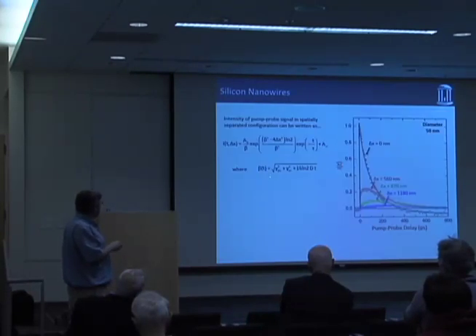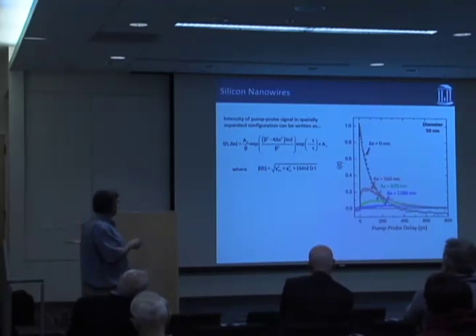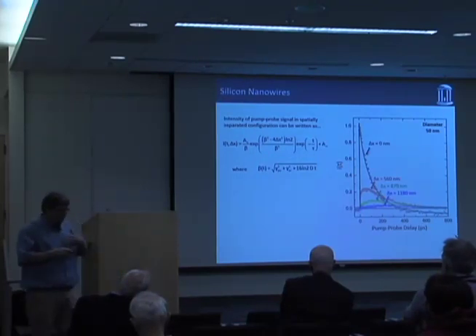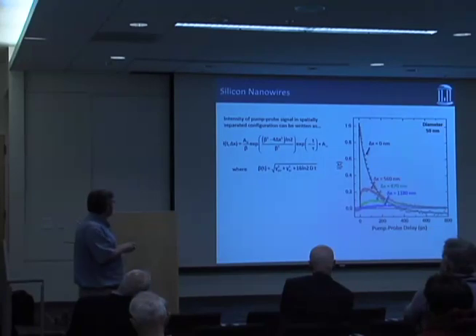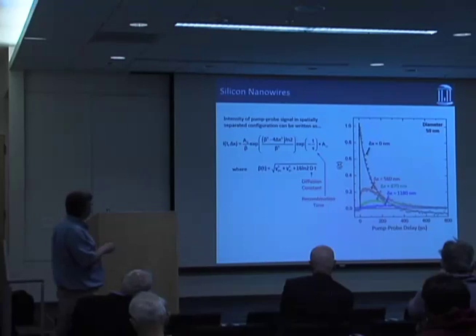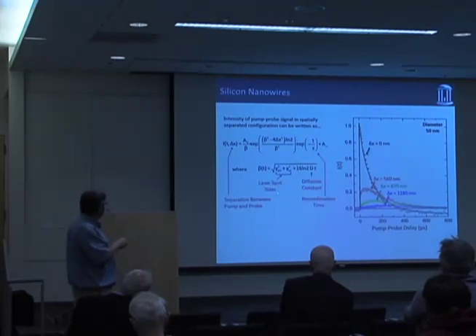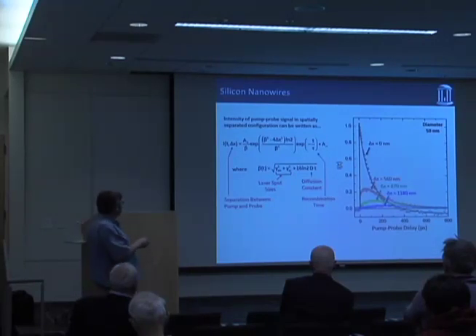We've gotten a little more sophisticated since we took that initial data, and now we actually have expressions where we can mathematically model these decays. So here's the intensity of our signal as a function of time and spatial separation, that's the delta x. What this does is it combines the diffusion equation with a single exponential decay, which has a lifetime tau. The diffusion constant enters into this equation, which isn't all that surprising. And then there are also parameters that have to do with the geometry of our experiment, particularly the laser spot sizes and so on. But I can take this equation and simultaneously fit all these different transients that we get out of the experiment and extract a single lifetime.